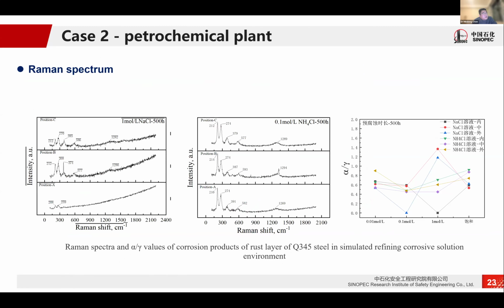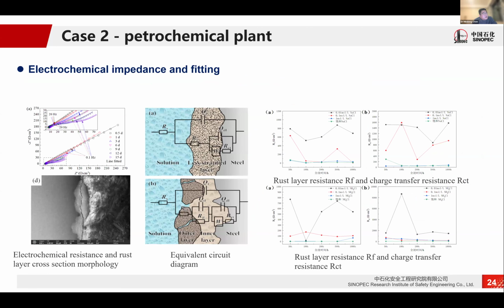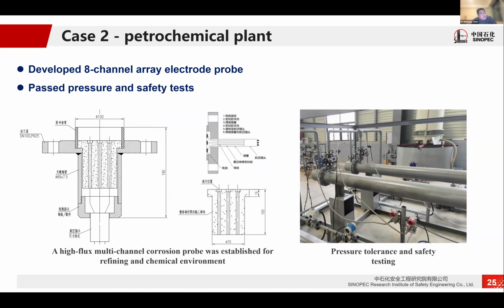And we also determined the alpha divided by gamma index by the Raman experiment. And we have done the electrochemical impedance and fitting, and we get the index of Rf and Rct. The experiments on the 3 slides above were all obtained in the laboratory.